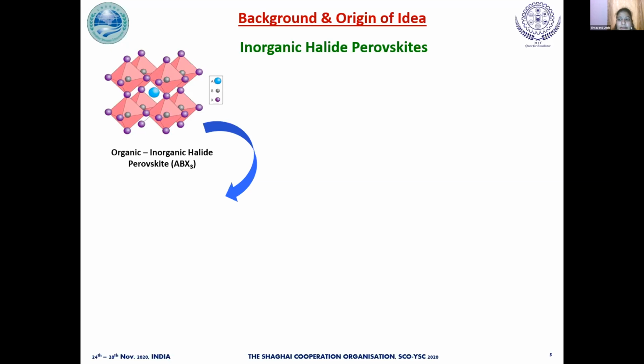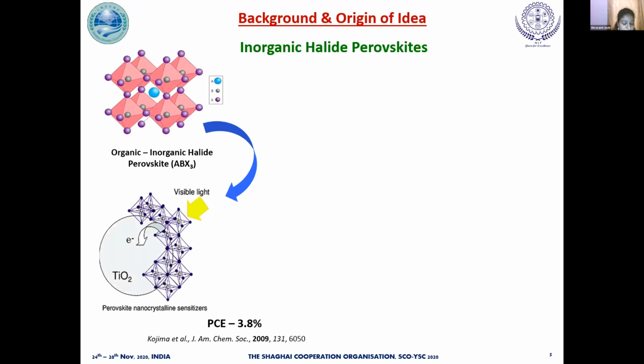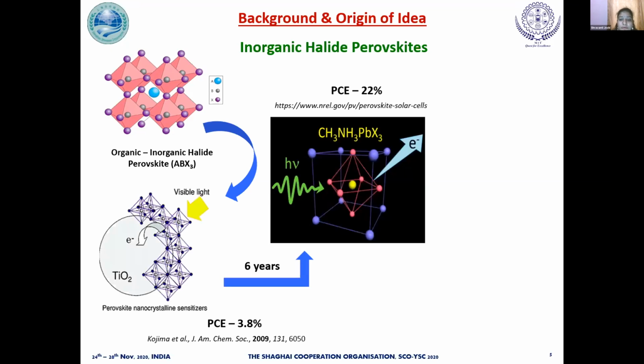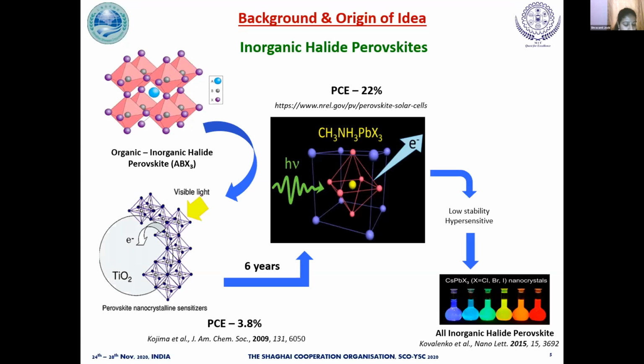when organic inorganic halide perovskite solar cells showed improvement in power conversion efficiency from an initial value of 3.8%, as reported by Kojima et al., to 22% in a matter of just 6 years. In the wake of such remarkable performances, a few demerits such as high sensitivity to humidity, oxygen, heat, as well as low stability restricted their use. Now, inspired by these drawbacks, in 2015, Kovalenko et al.